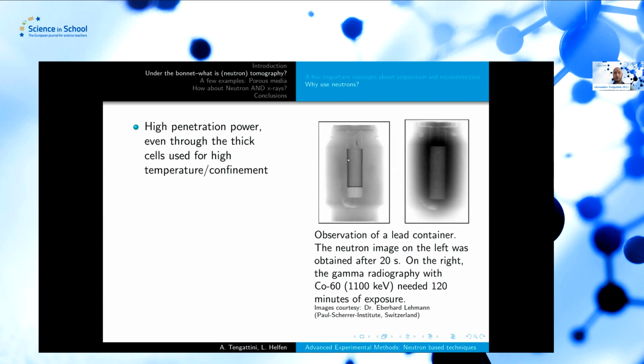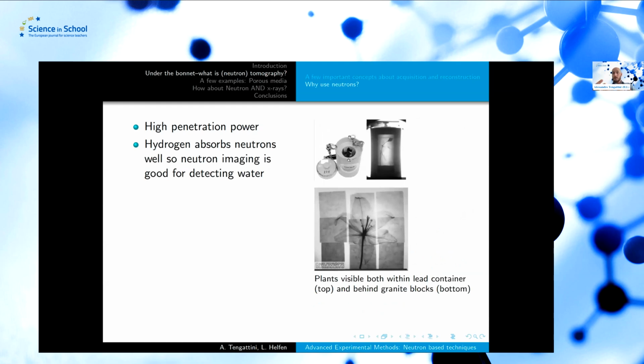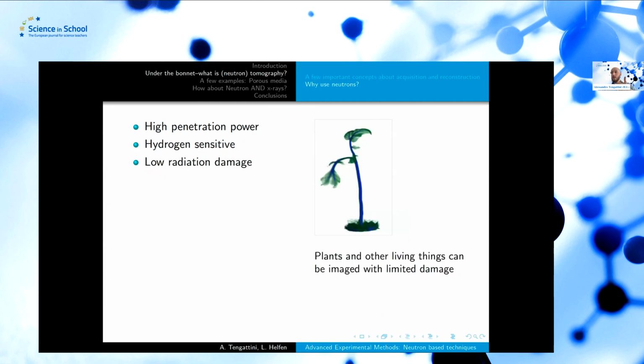I can just penetrate. Also, there are some elements such as hydrogen and lithium, which are very transparent to X-rays, but very, very opaque to neutrons. And this brings some beautifully paradoxical images, like if you put a flower behind a layer of granite, which is very dense, which is very hard to penetrate with X-rays, essentially you barely see it with the granite. With neutrons, you'll see very nicely the flower. Or if you take a flower and you put it in a container made of lead, you can see the flower and barely see the lead, which is in some cases very important to have this alternative penetration.